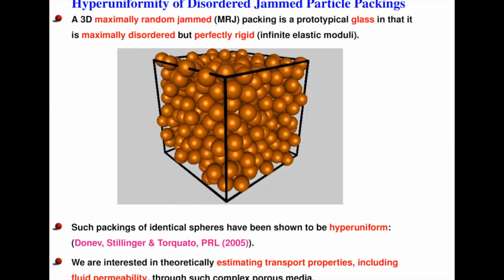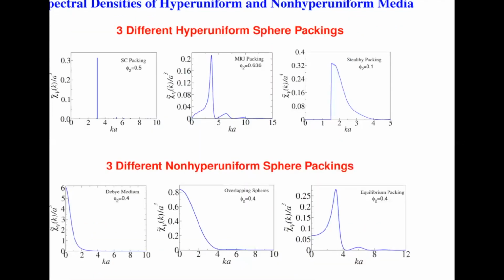Actually, since you're asking, when you look at the structure factor going to 0 at Q equals 0, then I would think about phase separation with a conserved order parameter. Then there you would see the structure factor go to 0. Is that then a hyperuniform state? Yeah, that's a very interesting question, Per. If you're talking about things like Cahn-Hilliard, spinodal decomposition, yes. We have shown in a separate paper that it actually is hyperuniform.